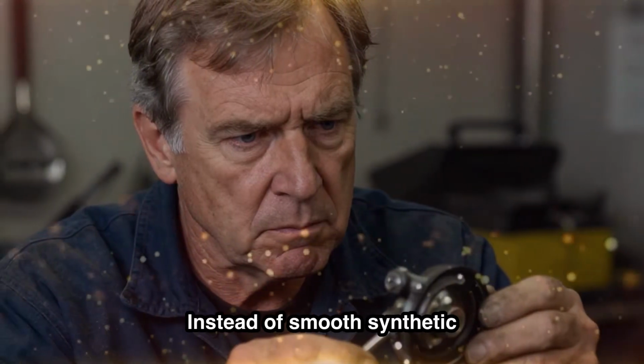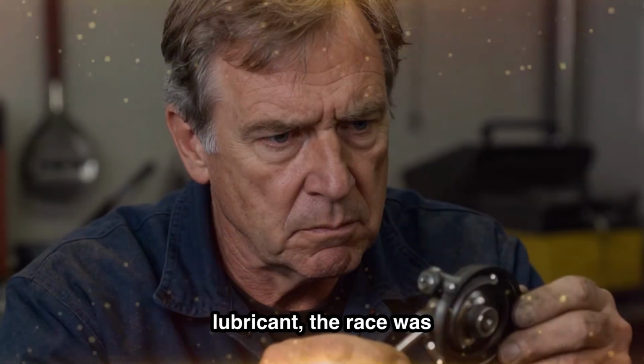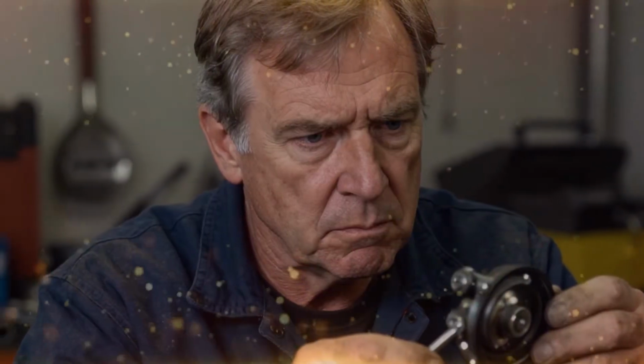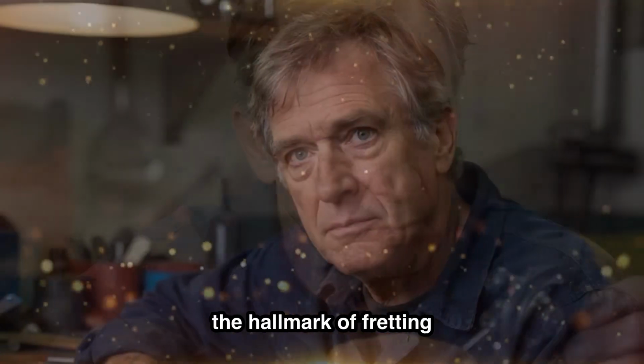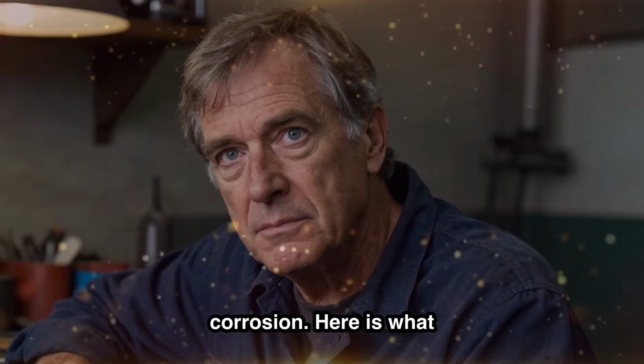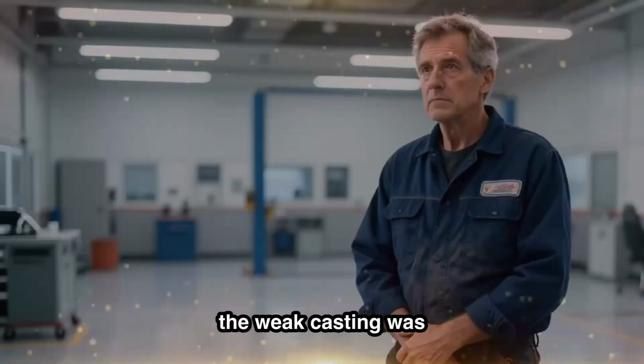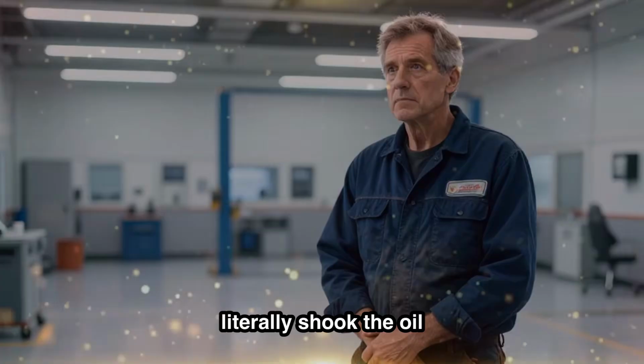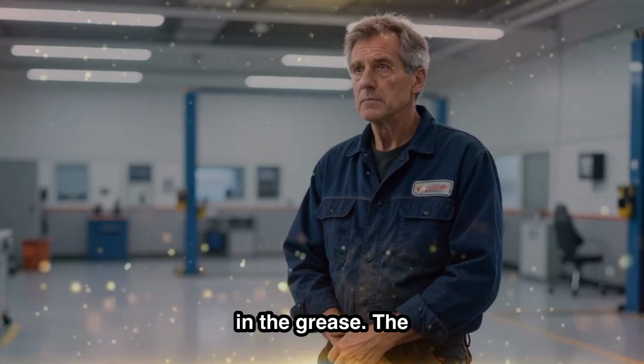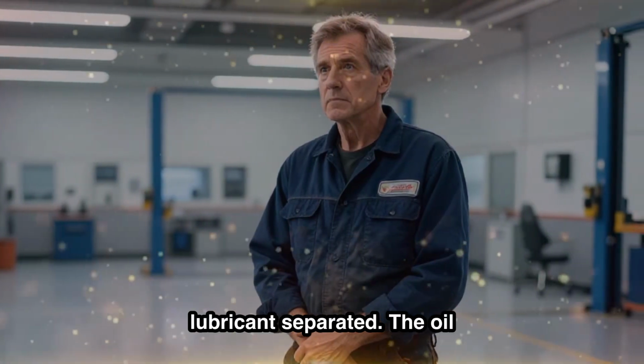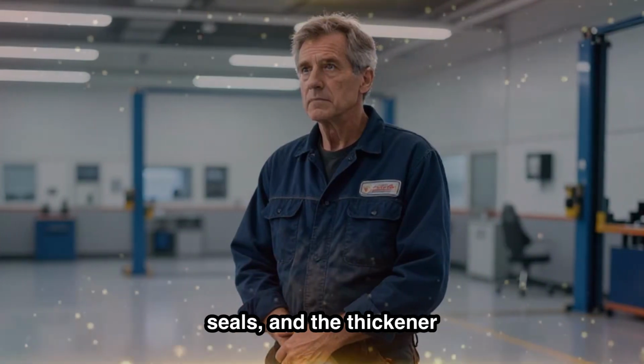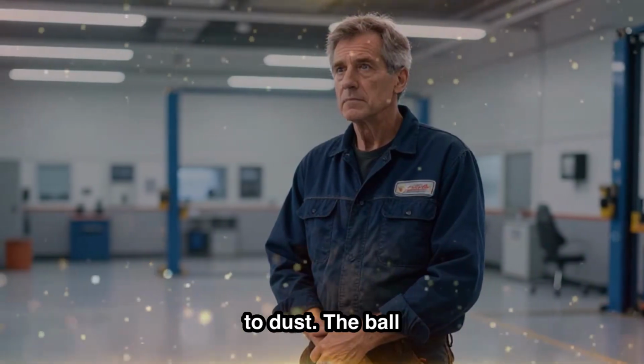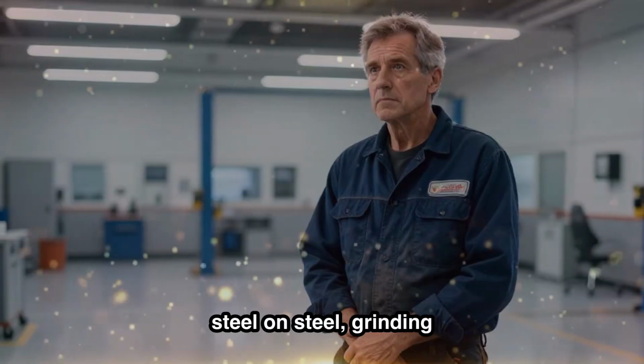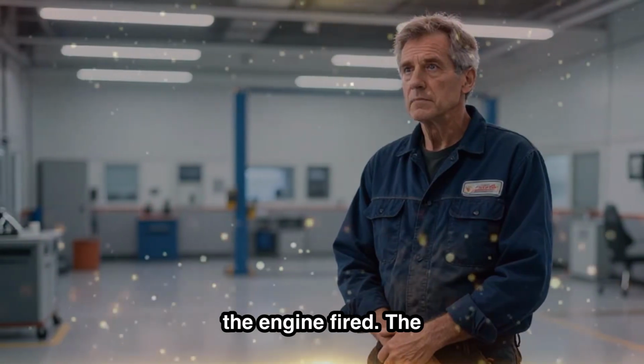It was bone dry. Instead of smooth synthetic lubricant, the race was filled with a fine, red powder. That is the hallmark of fretting corrosion. Here is what happened. The vibration from the weak casting was so intense that it literally shook the oil molecules out of the thickener in the grease. The lubricant separated, the oil leaked out past the seals, and the thickener turned to dust. The ball bearings were then running steel on steel, grinding themselves down every time the engine fired.